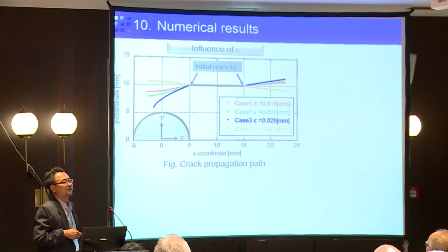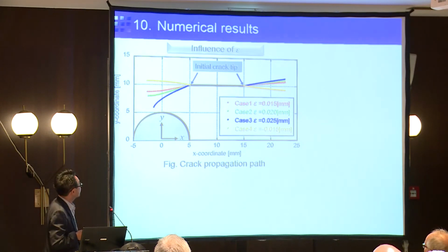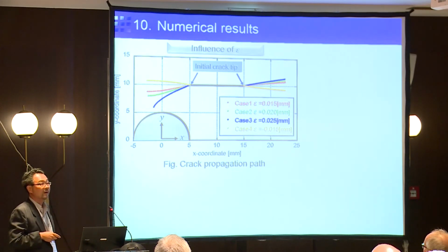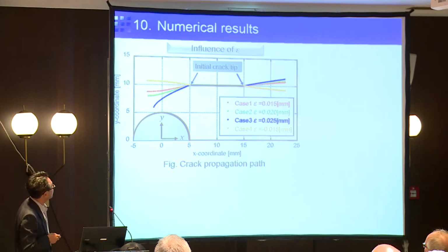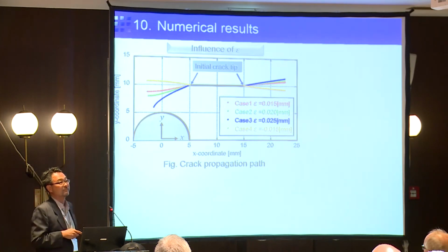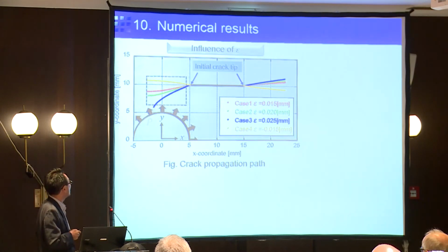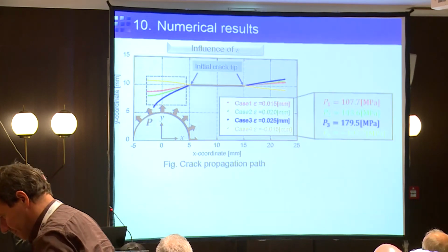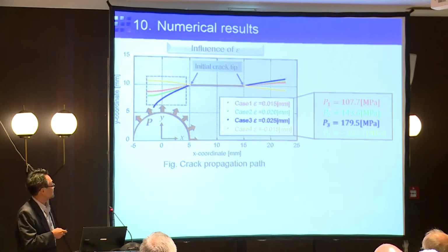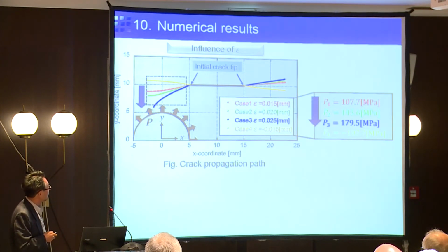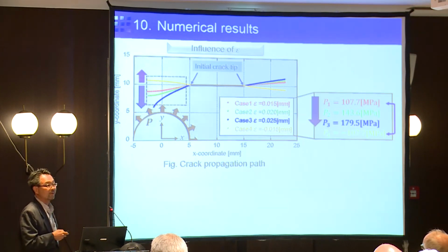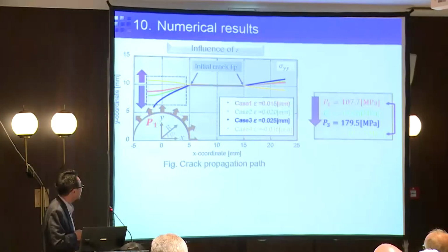But this is very interesting, because if we change to negative epsilon cases, the crack tip goes away from the precipitated inclusion. When we consider the pressure at the interface between the circular plate and the elastic plate, when epsilon is included, this value is also increasing, as shown here. From this result, the pressure change strongly affects the crack path geometry.